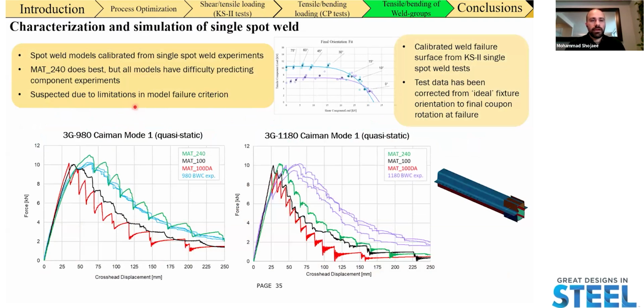Now, in terms of the calibrated Caiman models, you can see the results here, again, for the same three models. The model was calibrated using the weld failure surface from the single spot weld characterization test, and its accuracy was analyzed in the component test. You can see the comparison here, where we have relatively good agreement in terms of the peak load, but the energy absorption capability is being under-predicted.